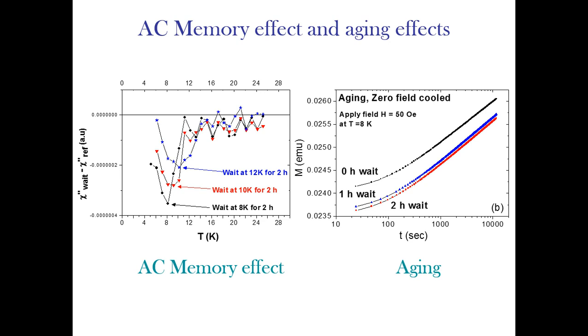And you can see clearly dips present at the waiting temperatures, because when we waited in the zero field cooled protocol, we increased the disorder in the system, and this is a clear hint of the presence of spin glass behavior.